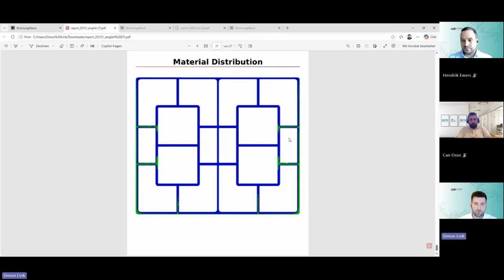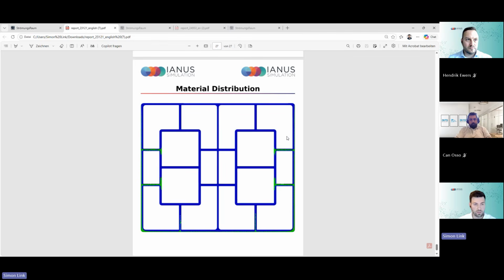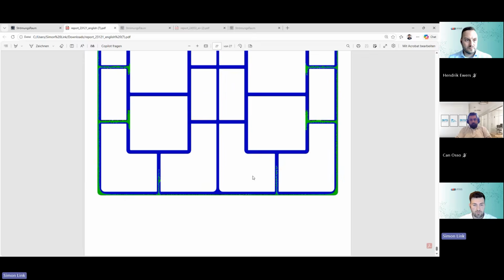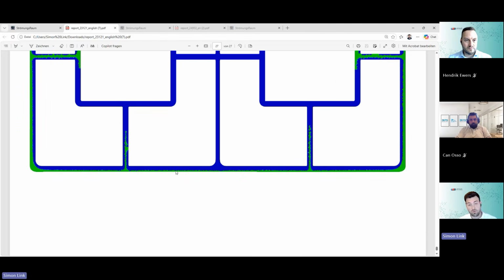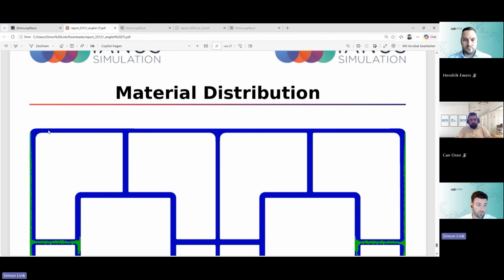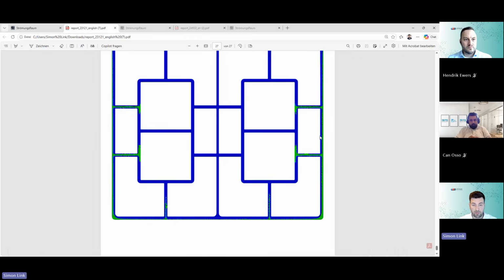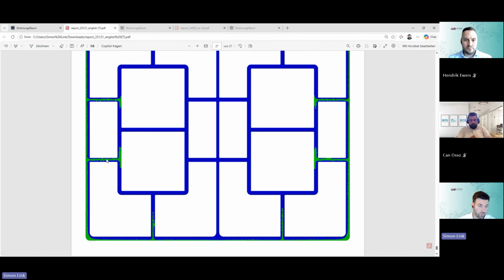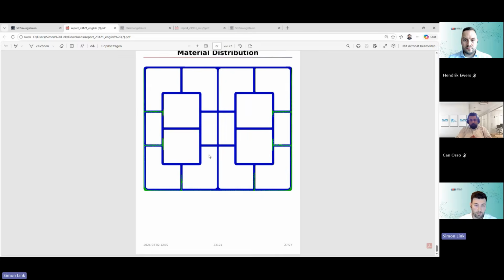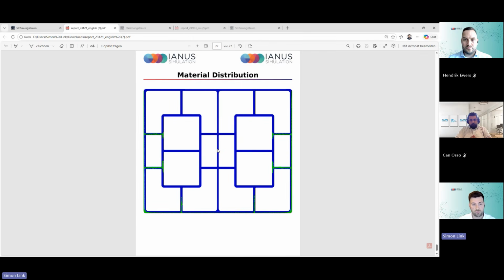What's also very interesting is here the material distribution, as you can see here. So this is a co-extrusion profile. We have two different materials. In the inside, we have the blue old material, and on the outside, there's this new virgin material in green. And we can detect the layer thickness, as you can see here. We can see, do we have a continuous layer or not? As you can see here on the top, the profile is not covered by the green material at all, and we can also see that the material here, the green one, is moving into the profile, and this makes it easier for us to do improvements to the tool even before the manufacturing.